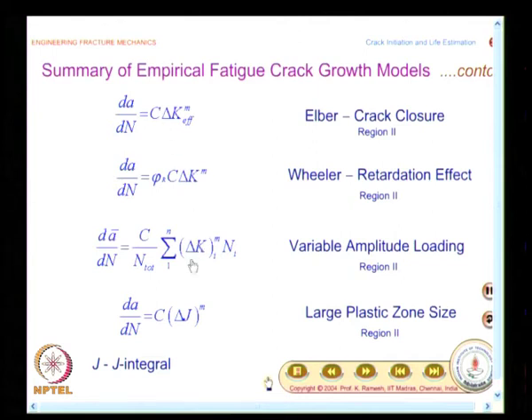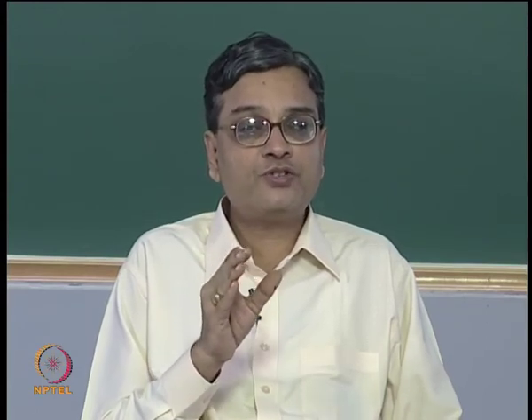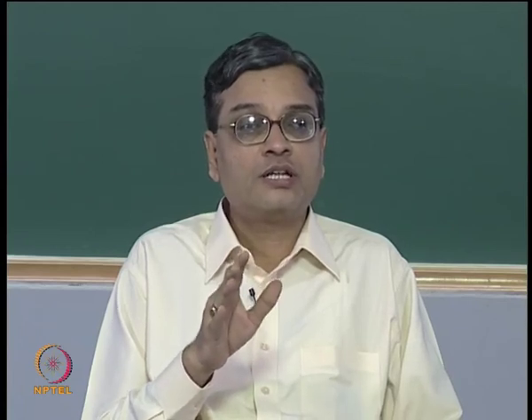After looking at the basic Paris law, people also have proposed, if you have a very large plastic zone size, you can also calculate dA/dN equal to C delta J power m, where J is the J integral. In fact, in the next class, we would understand what J is. So, these are all the modifications of the basic Paris law for different situations. One of the very important aspects of this part of the course is that it provides you a methodology to find out the crack growth rate for a variety of situations. You have laws that have been proposed by various people, and if you have access to these empirical constants for the material under study, you would be able to utilize them for your life prediction calculation.